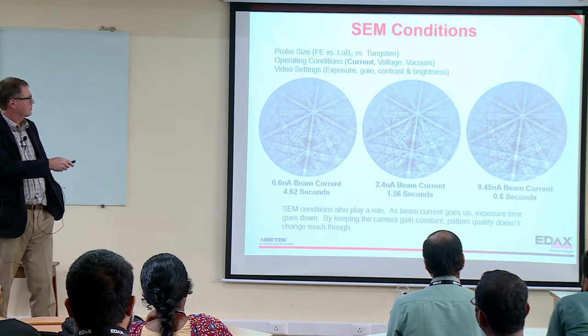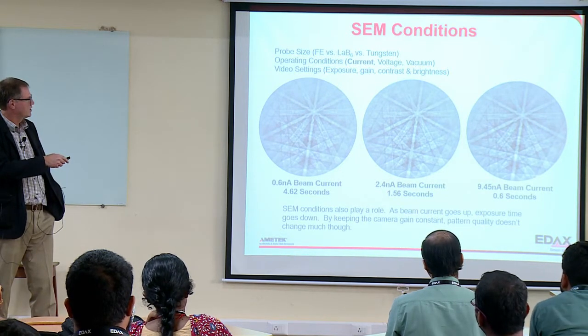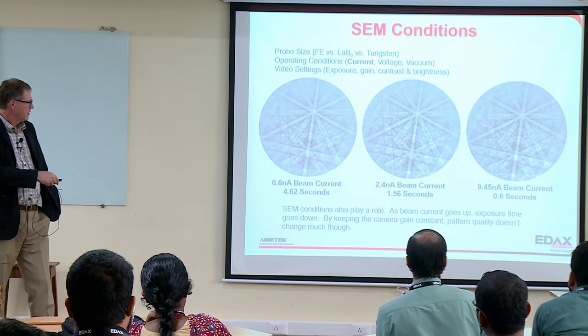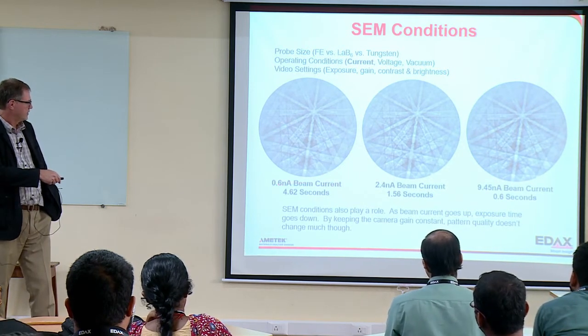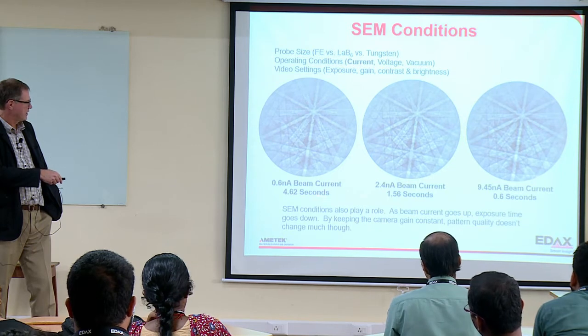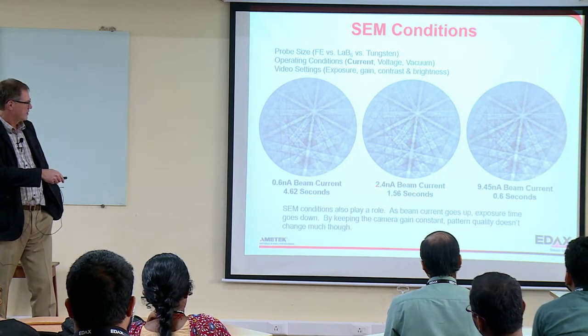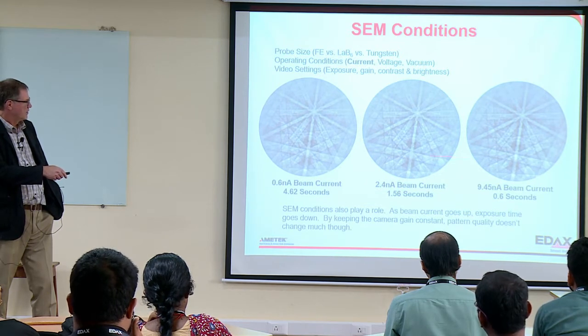In terms of the actual camera, you have things like exposure time and gain that you can play with. This is an example of 0.6 nanoamp beam current at 4.5 seconds, 1.5 seconds. You can see we've got a higher current, and here we have even more current. So we can go a lot faster, and the pattern quality is the same.